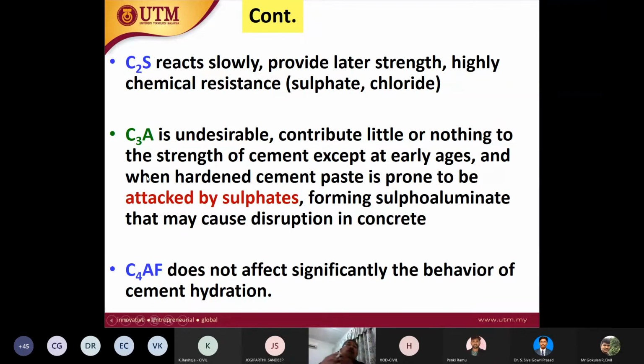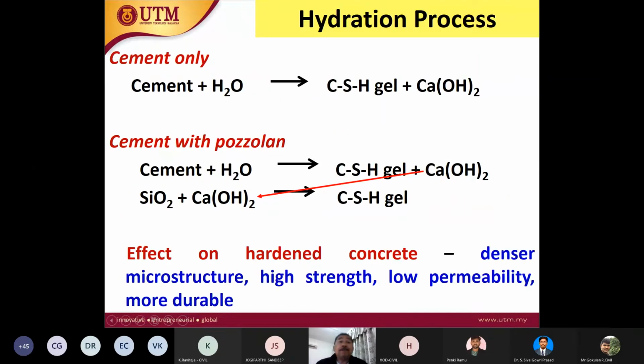So that's why if our structure is near the marine environment, it is not advisable to use just ordinary Portland cement. Why? Because ordinary Portland cement contains a higher amount of C3A, tricalcium aluminate. So that's why the tendency for sulfate attack is higher. All right. So the use of blended cement. Blended cement means a combination of ordinary Portland cement plus pozzolan material, fly ash or silica fume.